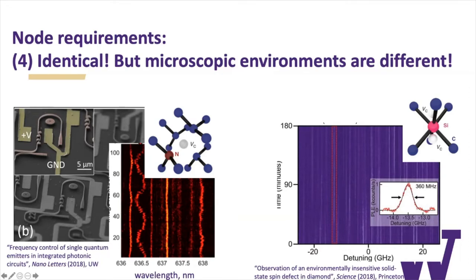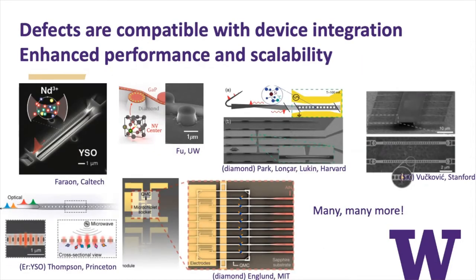Additionally, this is another example. This is the silicon vacancy center where again, if you look, you can see that each one is emitting at a little bit of a different wavelength. And here it's plotted in terms of frequency instead of wavelength. And in this case, the silicon vacancy, it's not due to electric fields because it's pretty insensitive due to the symmetry of this defect to electric fields, but it's very sensitive to strain. So each one of these defects in this crystal is at a slightly different energy because of the strain on the crystal. So even though the defects are slightly different, we have ways that we can try to tune them and also ways that we can alter their properties because they're in the solid state environment.